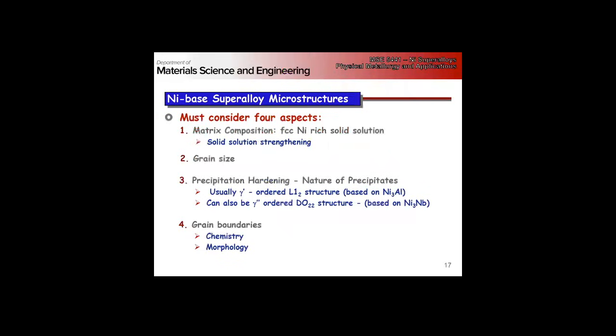On the last slide, you said that nickel or aluminum atoms might be located on nickel sites. That's possible - but would that be an anti-phase boundary mechanism to strengthen it, or? It can be, but you can also have just an ordering mismatch - you can also just have a site swap, it's just a different crystal defect.